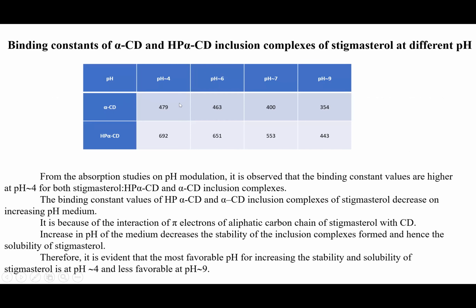So when we compare these binding constants between alpha CD and HP alpha CD complexes, for all the binding constant values, HP alpha CD is higher compared to alpha CD. Similarly, when we compare the pH values, pH 4 gets the higher binding value, that is at gastric pH. So the binding constant values of HP alpha CD and alpha CD inclusion complexes of stigmasterol decrease with increasing pH of the medium. It is because of the interaction of pi electrons of the aliphatic carbon chain of stigmasterol with the CD. So an increase in pH of the medium decreases the stability of the inclusion complexes formed, and hence the solubility of stigmasterol will also decrease.